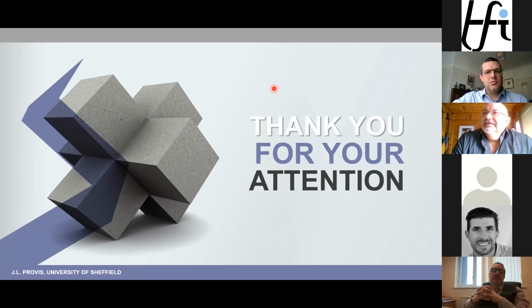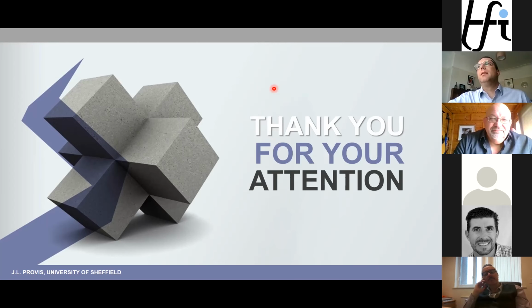Budaoud Mohammed asks, which method is the best to choose? The best kind of activation and ratio for the preparation of geopolymer for natural industrial waste? I guess he's asking about what's the best ratio of your components in your formulations, I suppose. Honestly, there is no substitute for laboratory test work. The way to find it is to look at what people have done before with similar materials and blend up a few possibilities using your own materials, identify what's working and refine experimentally. Actually, one of the challenges we have is that there's not an easy way to ab initio predict what is going to work for a given source of, let's say, less well characterized raw material. So what you need to do is basically trial some blends, see what works.